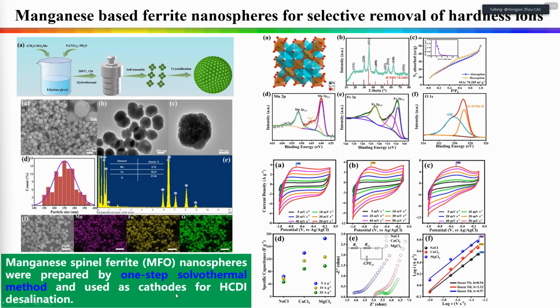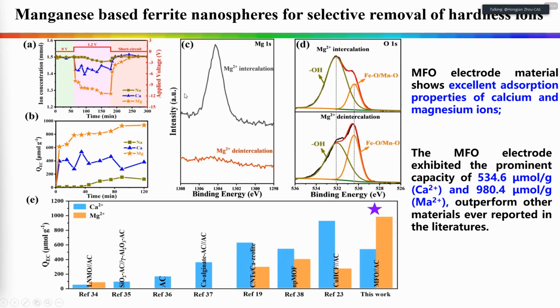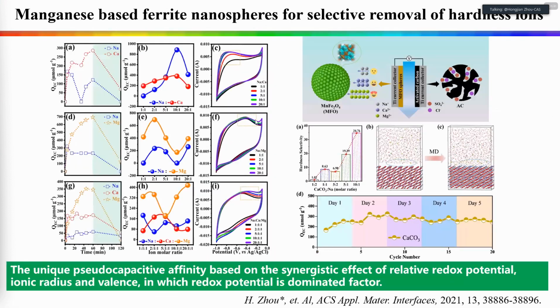We use this material as a cathode for hybrid CDI desalination. This is our material morphology and crystal characterization. This is the electrochemical performance. We can find that our material shows excellent adsorption for calcium and magnesium ions, with a prominent capacity of 534 micromole per gram for calcium ion and 980 micromole per gram for magnesium ion, which outperforms other reported materials. And in the end, we are also curious about the mechanism behind the material's selective removal of hardness ions.